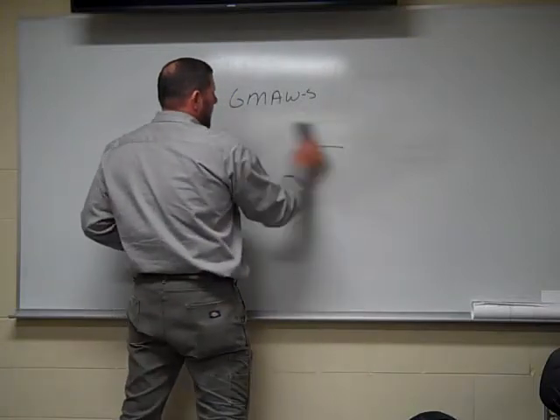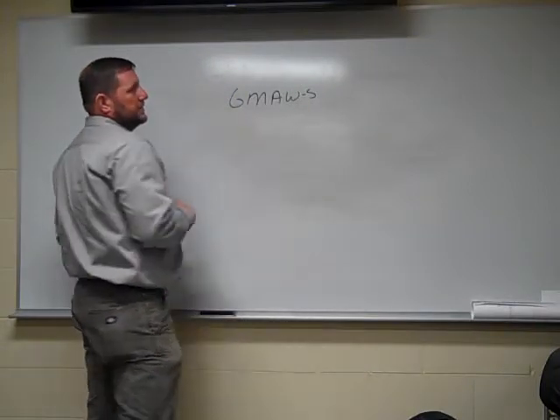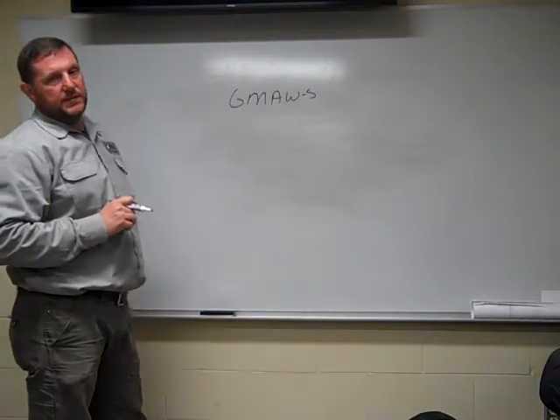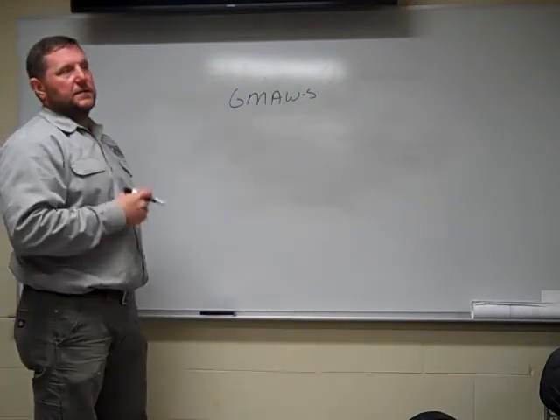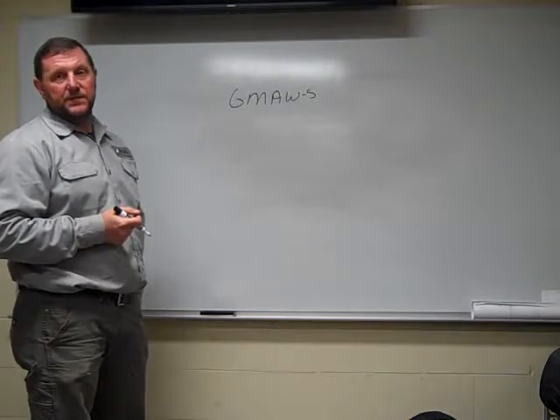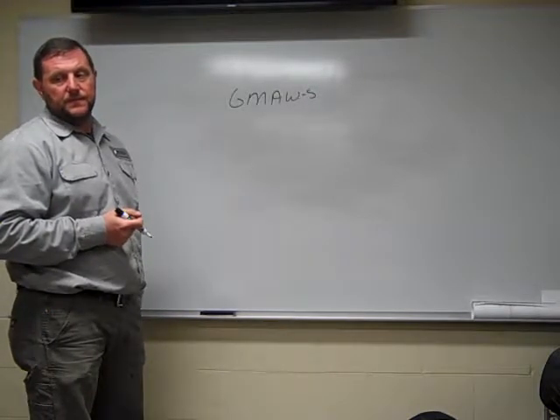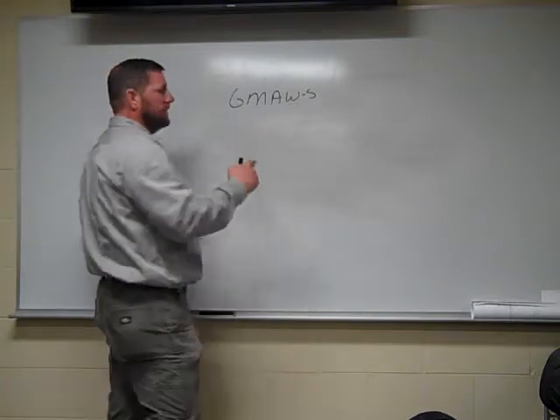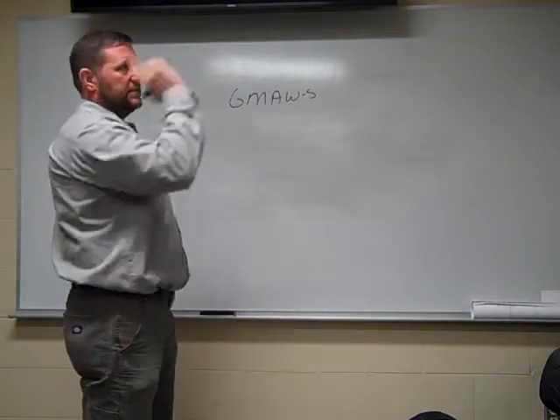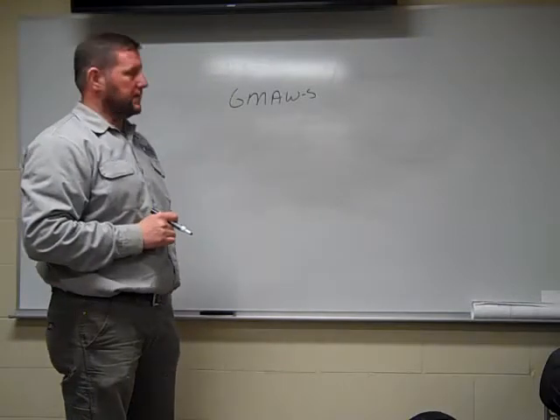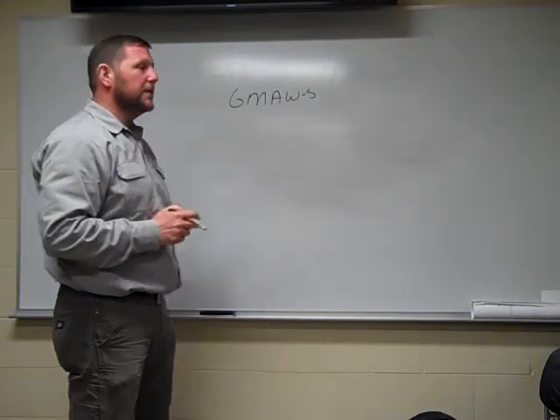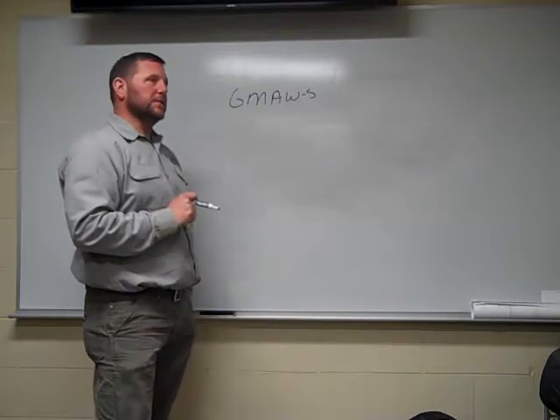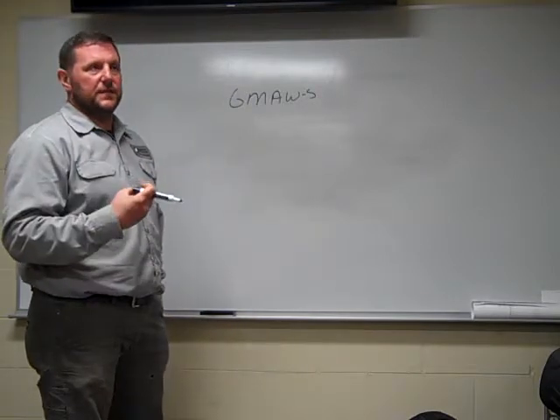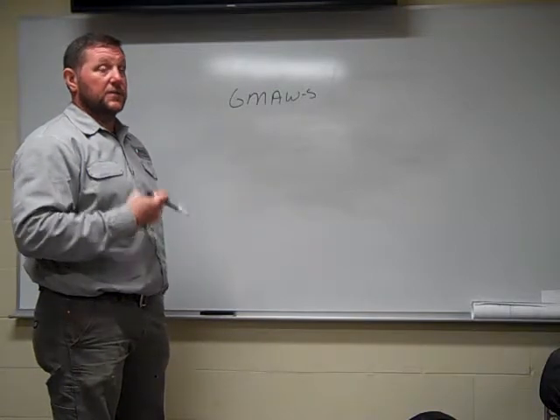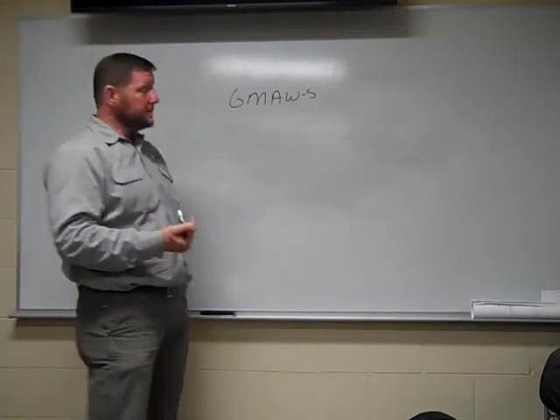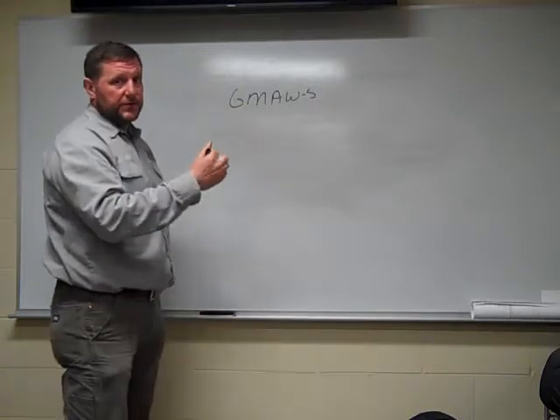Now, as you're putting in your passes or before you even start welding, if the material is outside, especially during winter, the temperature of that base metal should be at least 50 degrees before you actually start welding. Make sure it has a minimum of 50 degrees before you weld. So if you take a piece, let's say in January, you grab a piece out of the garage, you go over to the saw, you start cutting it, make sure you're at least 50 degrees before you weld it. That has a lot of characteristics of getting very brittle because it's actually cold metal when you actually start welding it. And your inner pass temperatures are very critical too.